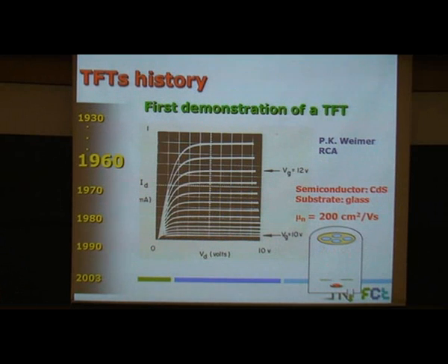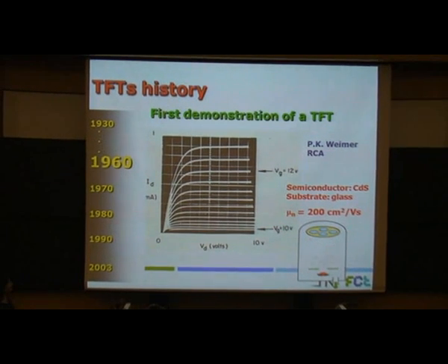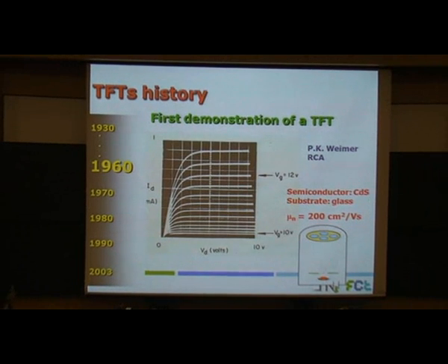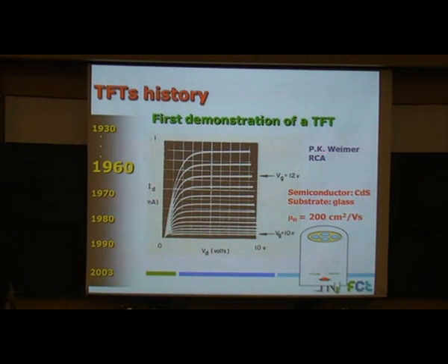Only around 30 years later came the first demonstration of a working field effect transistor, or thin film transistor. This was done by Professor Weimer at the RCA laboratory in the United States. This is the typical output characteristics of this TFT. He used a very simple system, a classical evaporation technique. He deposited cadmium sulfide on glass, a typical semiconductor used for photodetectors. And the mobility he achieved was very good, around 200 square centimeters per volt per second.